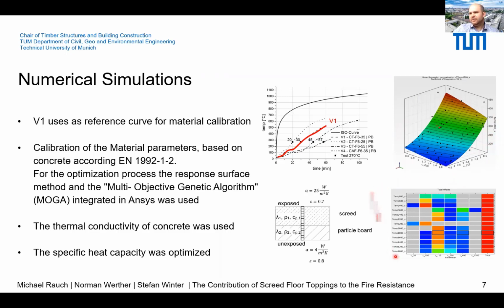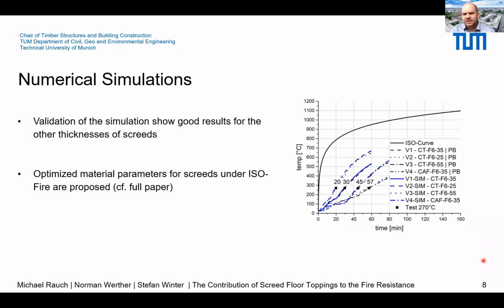The correlation of parameters show which parameters are relevant and which can be neglected for this optimization process. Based on these results, the thermal conductivity of concrete was used and the specific heat capacity of concrete was optimized to be used as an effective parameter for the screeds. The results of the numerical simulation compared to the fire tests with different thicknesses show a good accordance. You can see the results in the diagram on the right. The blue lines are the results of the simulation and the black lines are the fire tests. The optimized material parameters for screeds under ISO fire, which are proposed, are shown in the full paper.